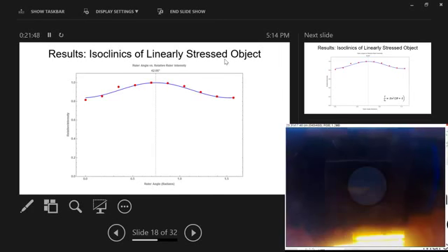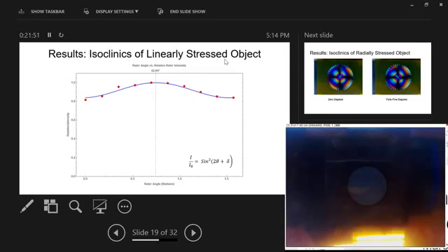This blue line I fit to it is a model that we determined based on the intensity model that I showed earlier. That intensity was for any given infinitesimal area segment, and it included that alpha term. Since we have a bulk material with many infinitesimal area segments, as we rotate through, that phase term will essentially be averaged out, because the phase will be randomly oriented through the material. So we just took that to be some constant factor and lumped it in with our I-naughts.